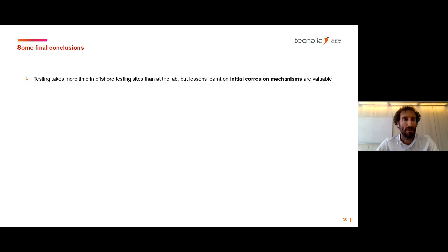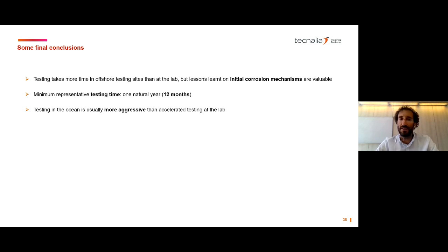So, final slides. Some final conclusions. Testing takes more time in the offshore environment than in the lab, but lessons learned on initial corrosion mechanisms are really valuable. We cannot simulate fouling in the lab, as I said a couple of times. Fouling can increase the corrosion rate in coatings. We observe it a lot of times, so that's really interesting. The minimum representative testing time is about 12 months, although shorter or longer testing can be performed as well. Testing in the ocean is usually more aggressive than testing in the lab, as we saw in the slides.